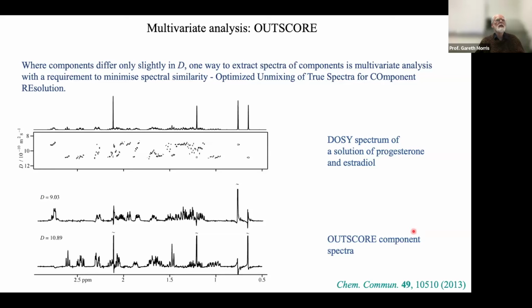And so we construct an algorithm that values difference between our component spectra. And with a really difficult problem here, large amounts of overlap, fairly similar diffusion coefficients, here we can extract pretty convincing spectra. There's just enough crosstalk there, a little artifact here compared with the very big methyl signal there, just enough crosstalk for us to feel fairly confident that we've actually done a good job here.